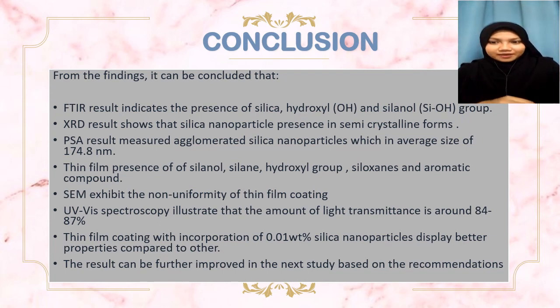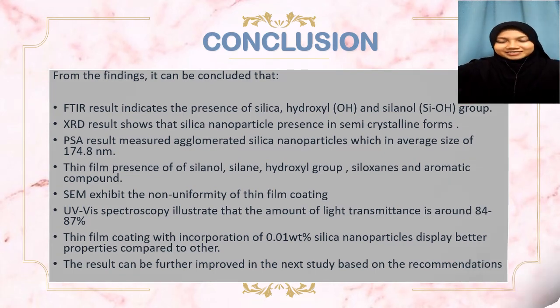And for the SEM, it exhibits the non-uniformity of the thin film coating with the agglomeration of silica nanoparticle. By the result, it can be concluded that the thin film coating with incorporation of 0.01 weight% of silica nanoparticle displays better properties compared to the others. However, the result can be further improved in the next study based on the recommendations.